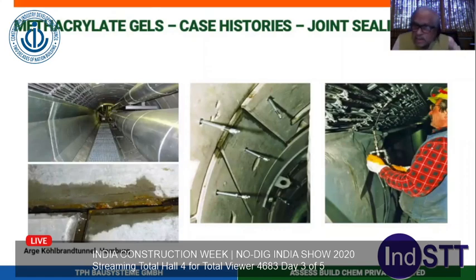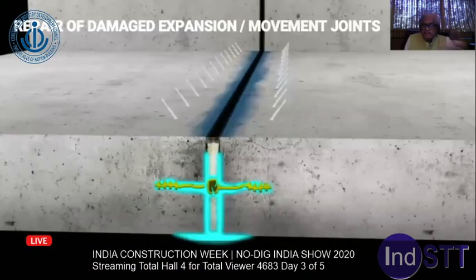Also, you can inject it from 2 different sides. You don't have to puncture. Sometimes you can directly puncture the gaskets and go behind them if the water entry is less. If the water entry is more, you can do it through the packers, which are put at 45 degrees. They go behind your gaskets and then create the same thing. The same technique, you are going behind that physical barrier.